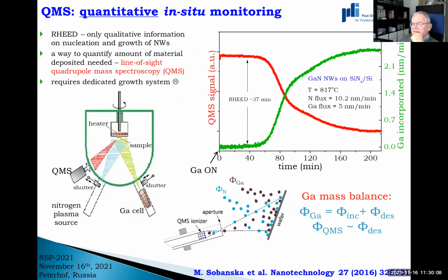Okay, and for getting insight into the processes going on at the surface, I will use two techniques. One is quadrupole mass spectrometry. It is a very simple technique: you take out one effusion cell from your machine and put the head of the spectrometer right in the position of the cell, so you measure line of sight. The spectrometer is calibrated in such a way that it measures the flux of gallium that is desorbed from the surface. So we deliver some gallium to the surface, part of this gallium is desorbed, and this is what is measured by the system. In real life, it looks like this red curve, this is the signal that we measure. At the beginning, all the gallium delivered to the substrate is desorbed, then desorption decreases, as you see here.